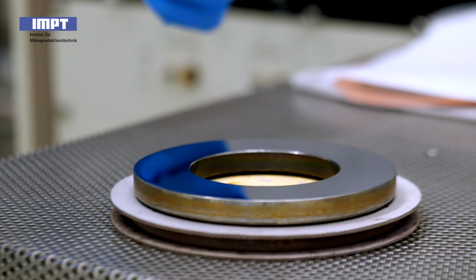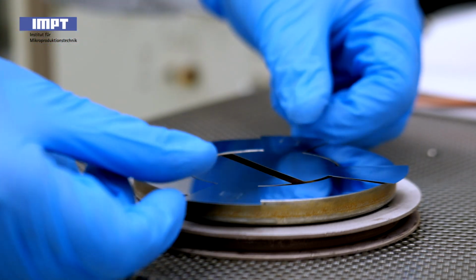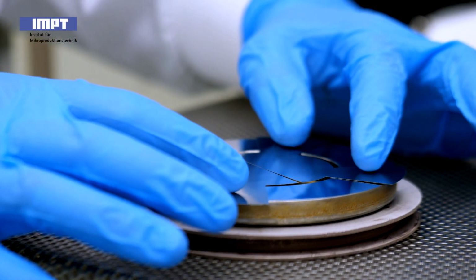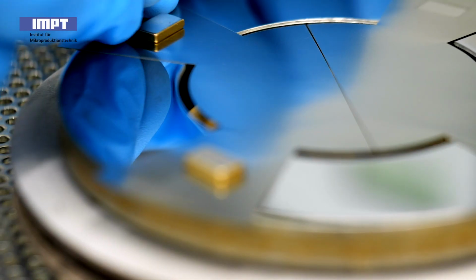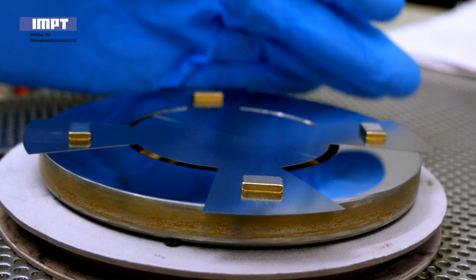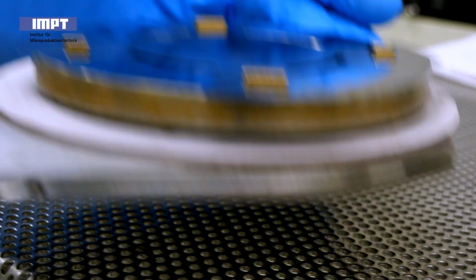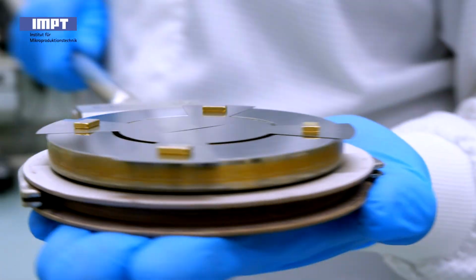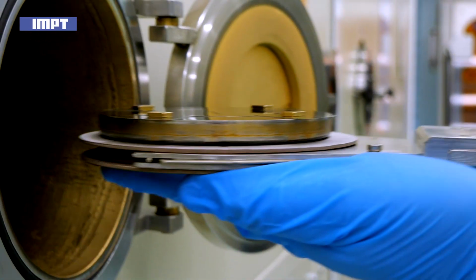This is followed by the deposition of the two sensor materials, deposited in different areas with the help of shadow masks. We use Constantan for the strain gauges. It is ideal because it has an almost temperature-independent resistance. In other words, a very low temperature coefficient of resistance, TCR, close to zero.